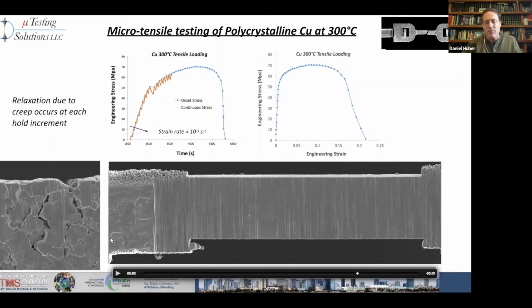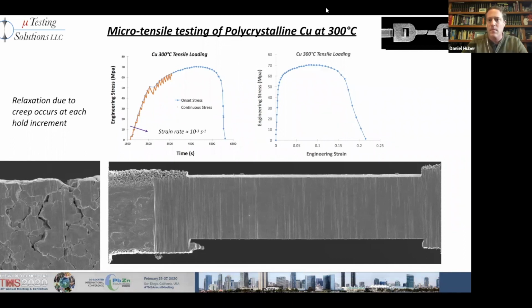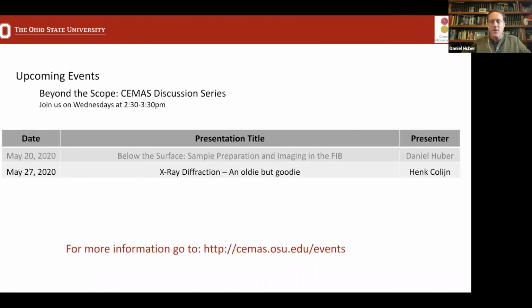So this has been really useful for studying interfaces and weld materials. Dissimilar joining and stuff where you've got two different materials. It'd be almost impossible to go back and test in bulk what the material at the interface might be in terms of its strength and properties, where now with the FIB we can go select a very small area, say of a weld, and then test that material and find out what its properties are. That's useful for putting that information back into models for predicting what the properties and stuff might be. And so those are some of the things that we can do.